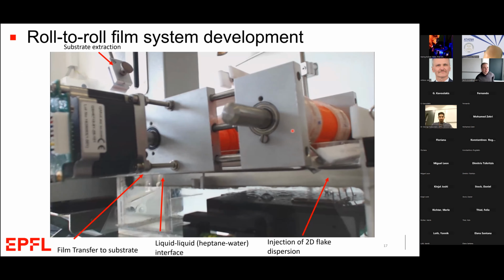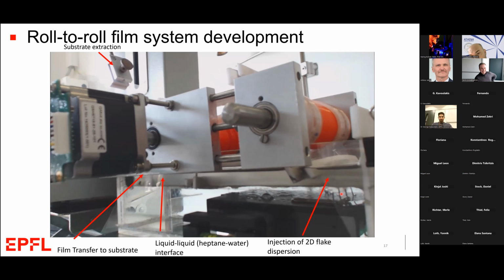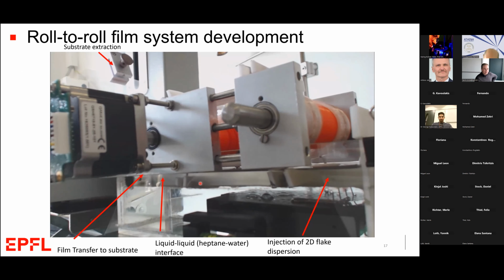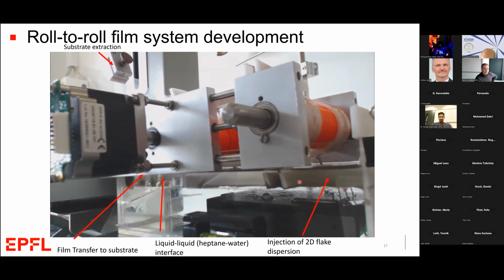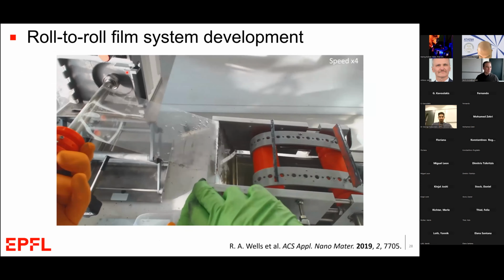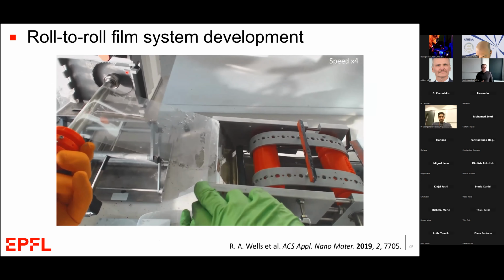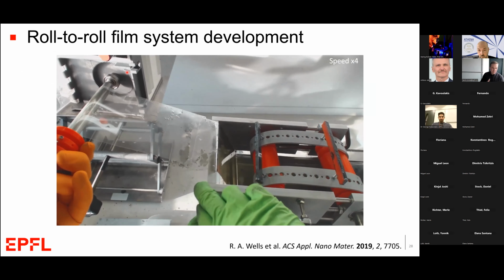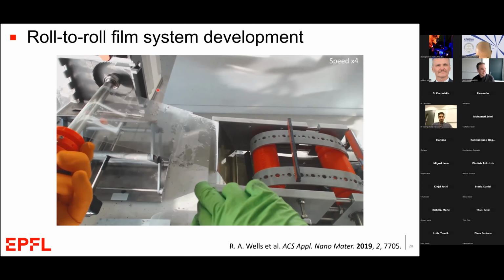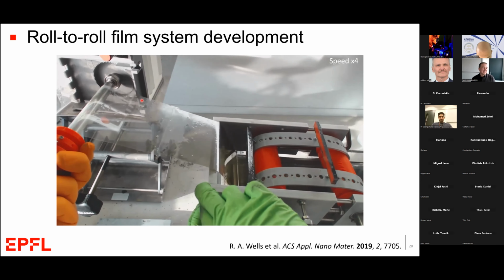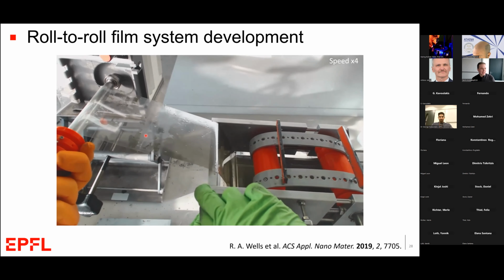Using a 3D printer and a stepper motor, we were able to develop this system where we can inject our flake dispersions here from the bottom. And here's our liquid-liquid interface. The nanoparticles assemble at this liquid-liquid interface, and then we push the film towards this substrate, which is being extracted here. And there's another view of it a little bit better. This is sped up 4 times because we have to do this a little bit slow and careful. And at least in principle, we can use